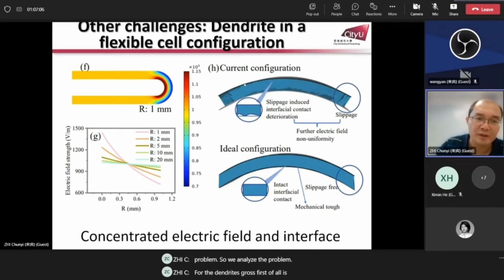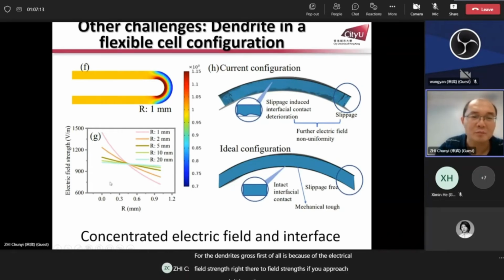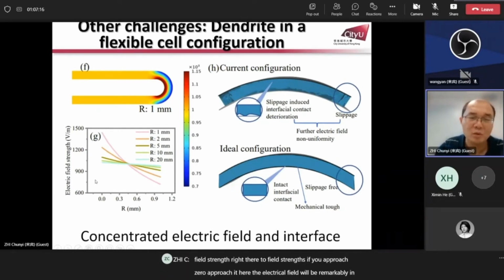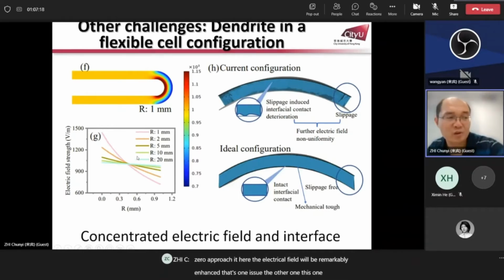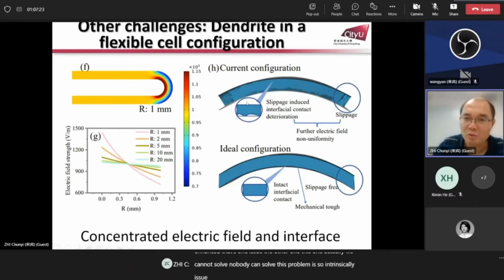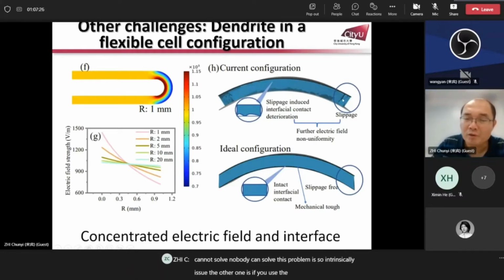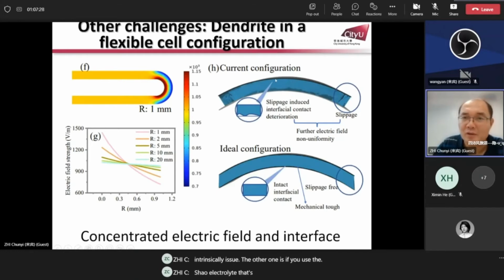First of all, it's because of the electric field strength, right? If you approach zero, here, the electric field will be remarkably enhanced. That's one issue. The other one, this one actually we cannot solve. Nobody can solve this problem. It's an intrinsic issue. The other one is if you use a gel electrolyte that's in contact with the electrode, when you bend it there is detachment between the gel electrolyte and the zinc electrode. So this one will also generate non-uniformity.